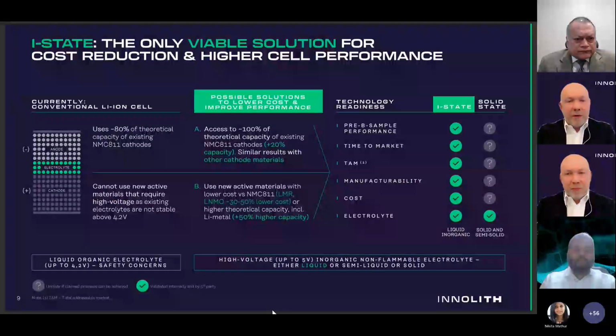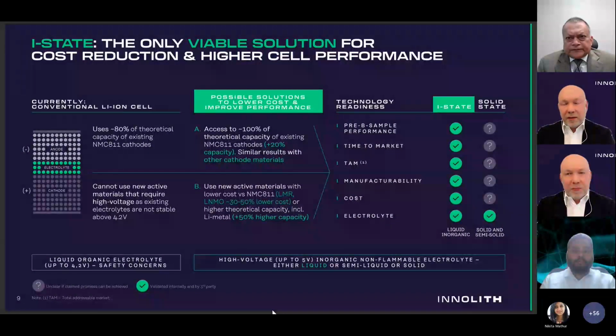How it works. On the first line, you can see that a conventional system usually utilizes about 80% of available lithium on the cathode side. And in case A, our electrolyte gets access to almost 100%. That's how we increase utilization of available cathode material, and we increase energy density in the cell, plus we add the performance that comes with our electrolyte. And below, what I've mentioned earlier, the use of new materials, that is case B that we've shown in the previous slides, versus some of the solid state technologies.